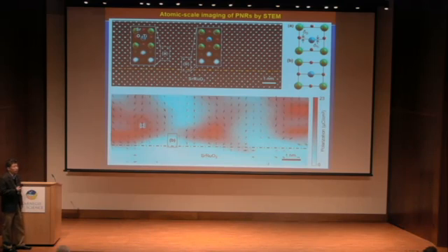And STEM is very challenging because the displacement measurement is very difficult. It's a very small amount of displacement. What we did here is, you can see that there are certain regions, and this oxygen and this oxygen with respect to the titanium. You can see the displacement with respect to this ion, and in this region there's no displacement.